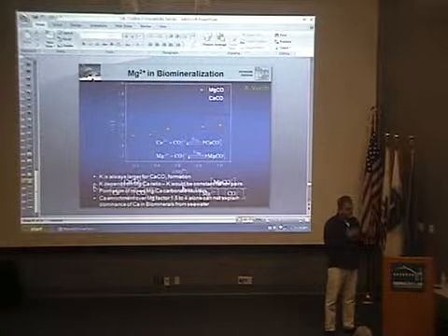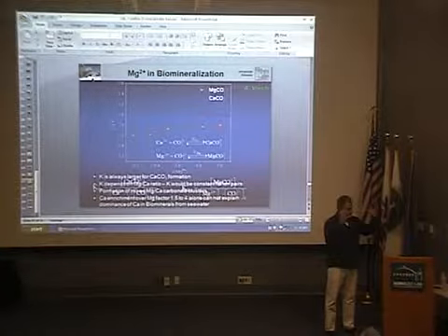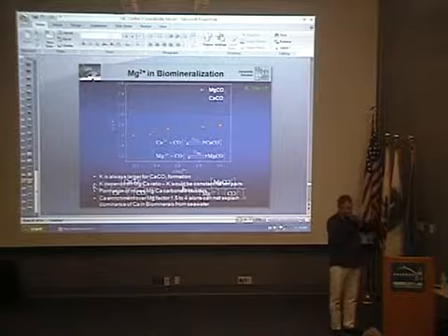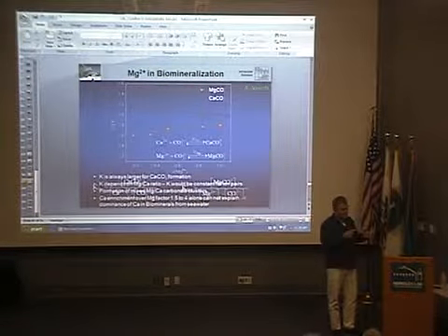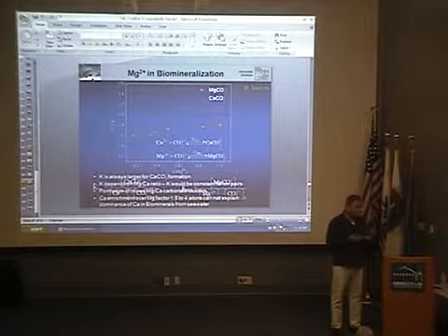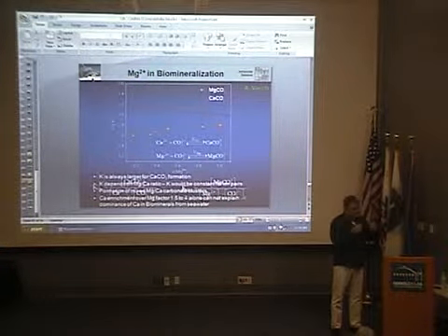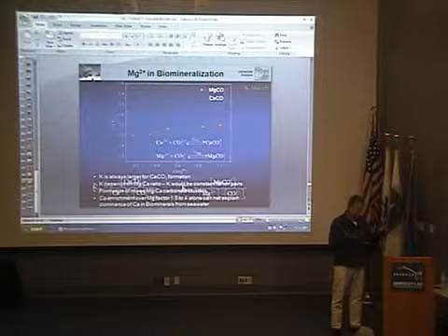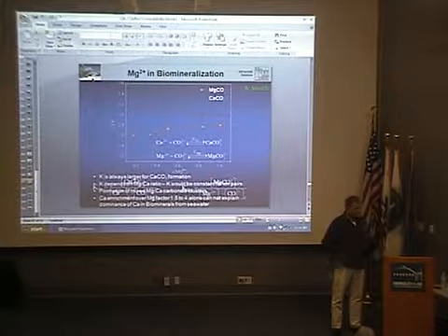So what you have at this point is that you have the aggregation of clusters which already occurs before the nucleation point. You get the macroscopic precipitation at that point, if you look at it with a microscope, but also the drop in calcium concentration. So it's very likely that the ions must add to the precipitated species because solubility remains constant. So it's, if you wish so, it's a seed, yeah, which grows by further ion addition.